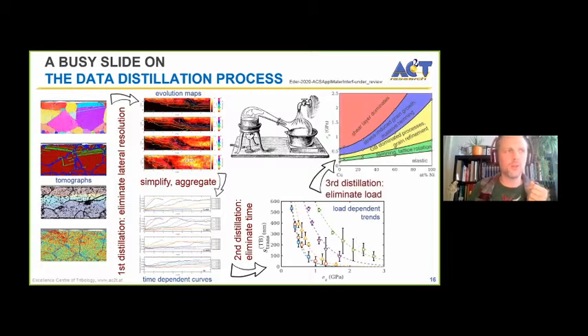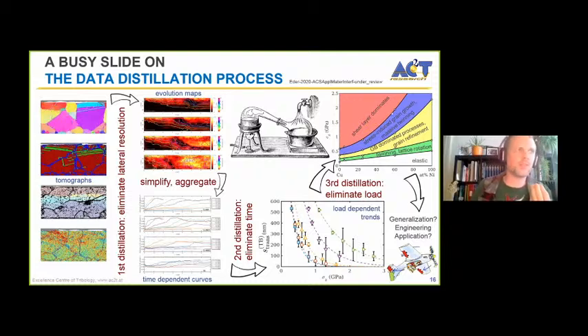And then you can associate those and, after the elimination of load, feed those into this 2-dimensional map where you have the alloying, the composition, on the horizontal axis, the normal pressure on the vertical axis, and then it basically nicely falls apart into regimes where you have purely elastic deformation, twinning and incipient twinning and lattice rotation, you have grain refinement, massive twinning and stress-induced grain growth, and the point where the shear layer just dominates your entire system. And we are hoping that this might be generalized at some point. We're not there yet, but this is currently under review.